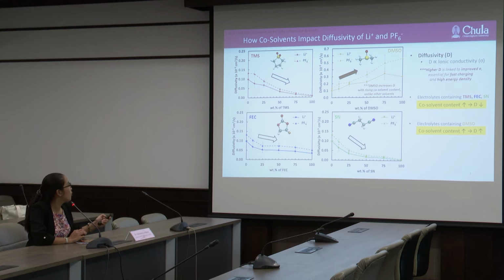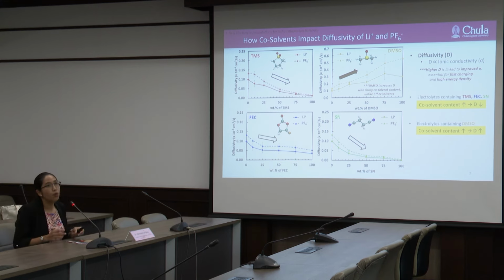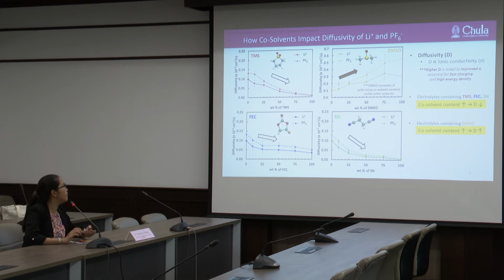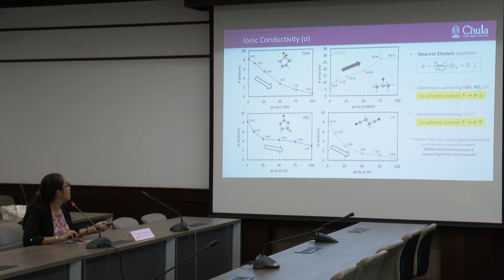We examine how co-solvent impact diffusivity of lithium ion and PF6 anions. And in general, high diffusivity is linked to improved ionic conductivity, which is important for fast charging and high energy density. And what we observe here, DMSO increased diffusivity with rising co-solvent content, unlike TMS or FEC or SN. We use the Nernst-Einstein equation to calculate ionic conductivity, and we find that while TMS, FEC, and SN show reduced ionic conductivity as co-solvent content increases, DMSO exhibits enhanced ionic conductivity. This supports better ion movement.